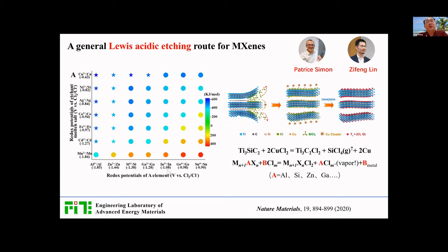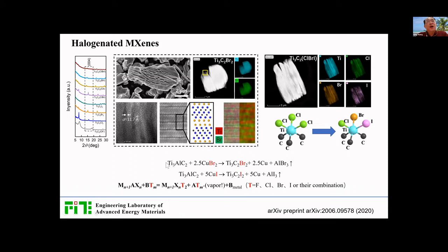Here we have a collaboration with Professor Patrice Simon and Dr. Zifeng Lin, and we found that through this approach, the final MXene products should be very promising for energy storage in long-cycle battery systems. I will not discuss the details here. And we can choose some other melts where we change the anion systems. Here I show that if we use a bromine melt and also an iodine melt, we can change the terminals of the final MXene product.